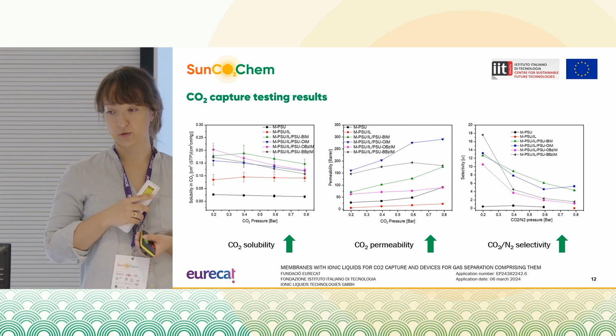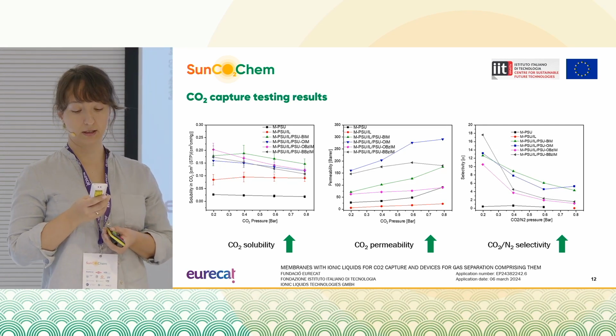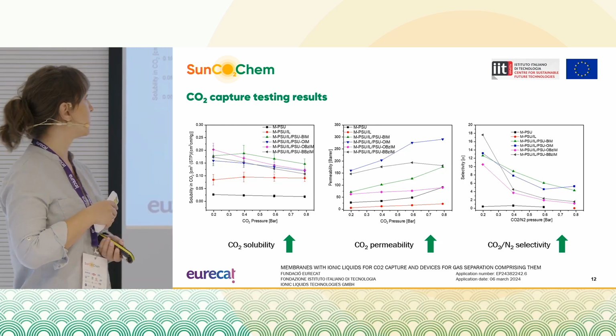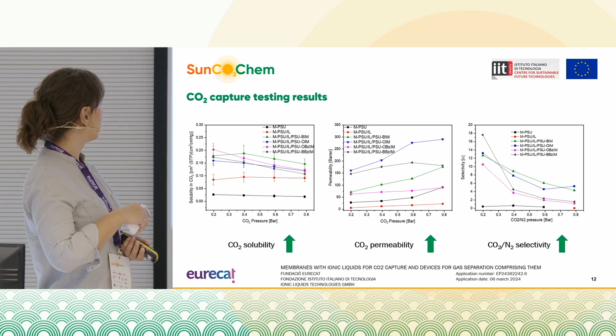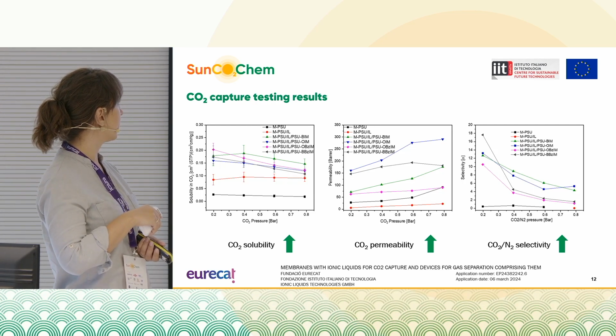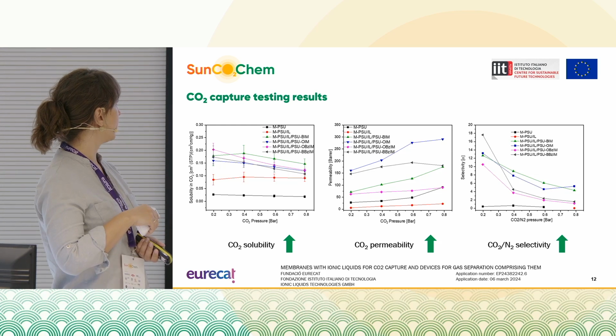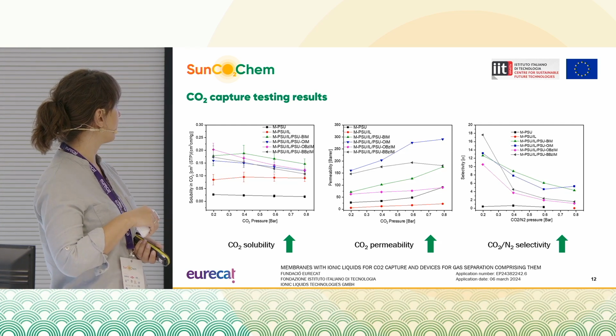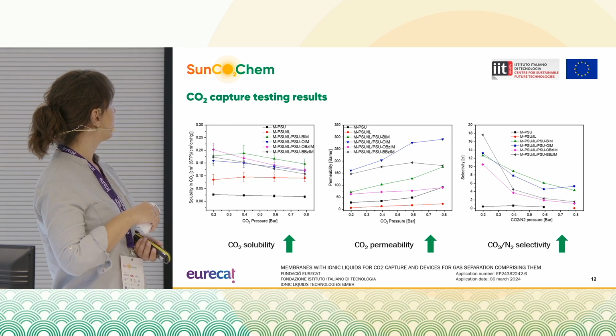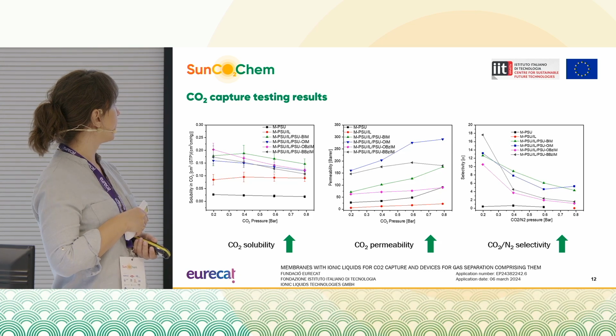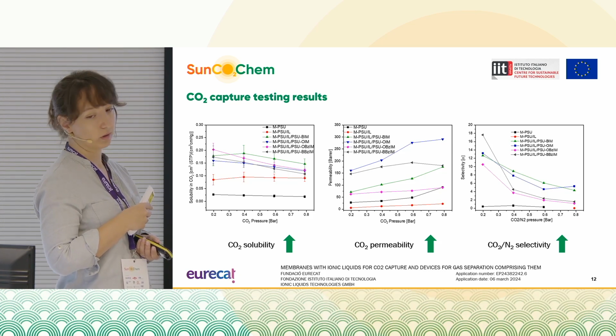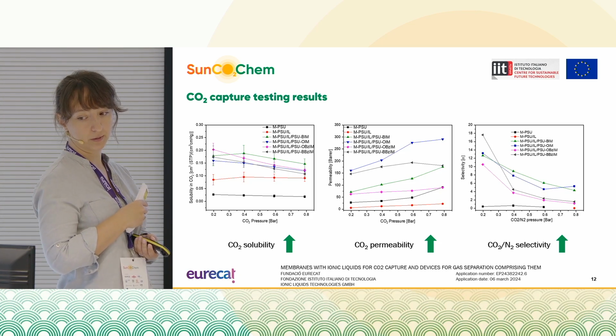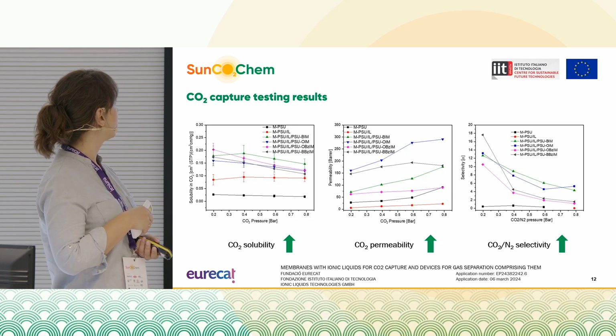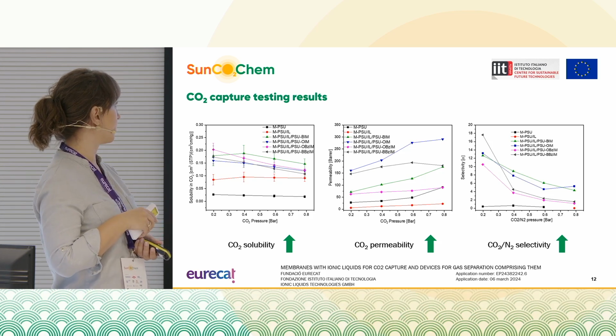Those are the results obtained from the testing. As you can see, the CO2 solubility increased once we introduced physically ionic liquids in comparison to a blank polysulfone membrane. And then each addition of a new polymer that was modified with ionic liquids, it increased even more the solubility.